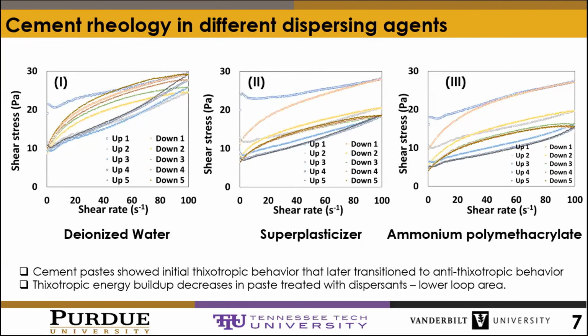And as you can see, upon transition, the area inside the anti-thixotropic hysteresis loop is larger for paste in deionized water than the other two doped pastes. And this indicates that both agents seem to reduce the anti-thixotropic energy storage. And this is caused by reducing frictional interaction.